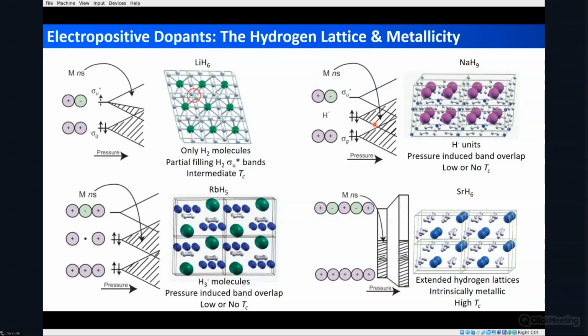So these types of systems are usually not very good high temperature superconductors because of this low density of states at the Fermi level. Another hydrogen motif that one can find in these high TC hydrides would be the formation of H3 minus type units. And here I show the cartoon molecular orbital diagram of H3 minus. Again, we have this large gap between the bonding or the antibonding and the non-bonding orbital. And under pressure, we get an overlap of these bands formed from these orbitals.